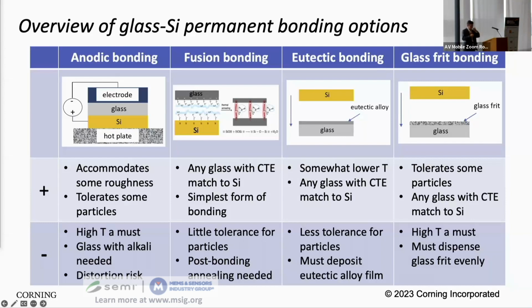Anodic bonding is relying on high temperature and the glass producing a mobile ion, mostly sodium. And if you apply a voltage, then the sodium moves, and the oxygen moves in the other direction, and the oxygen can combine with silicon to form a silicon dioxide at the glass-silicon interface. And that's how you form a hermetic seal. So this is very commonly used in the MEMS industry.